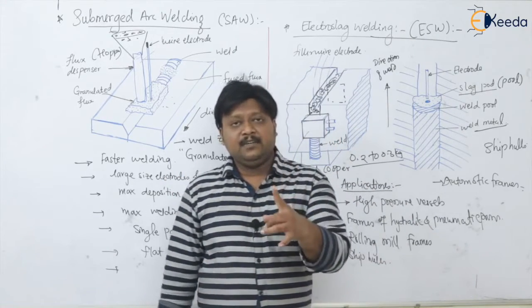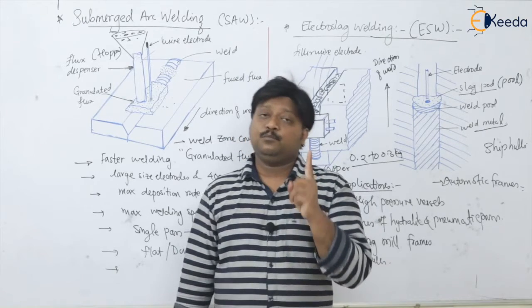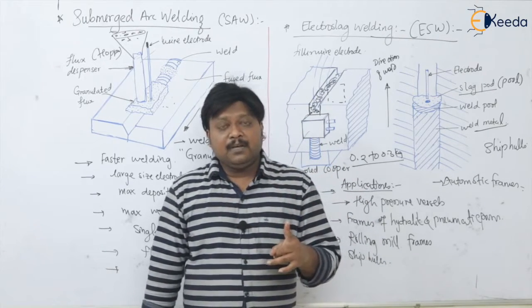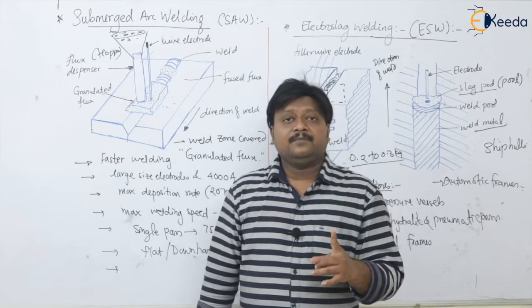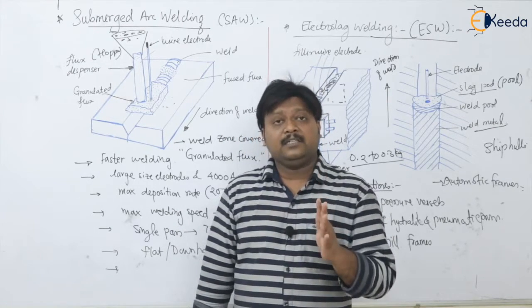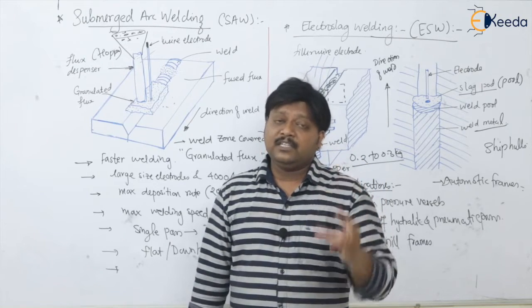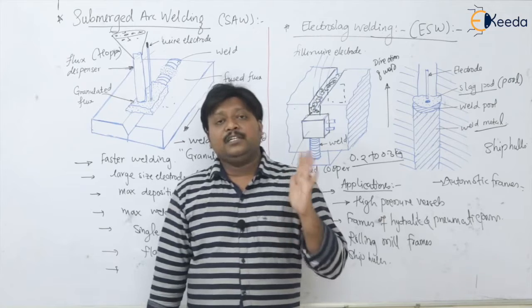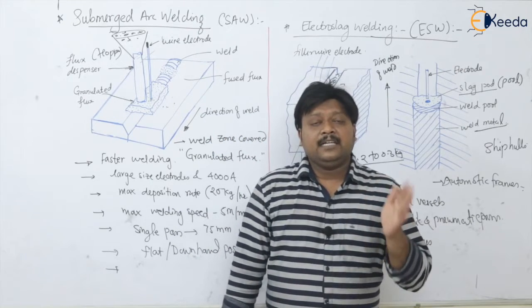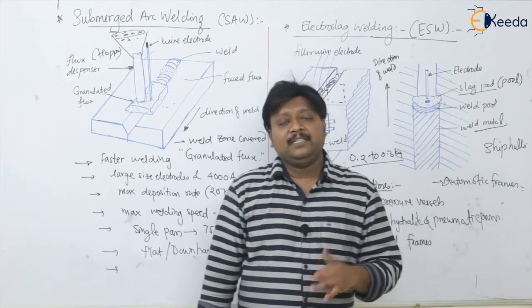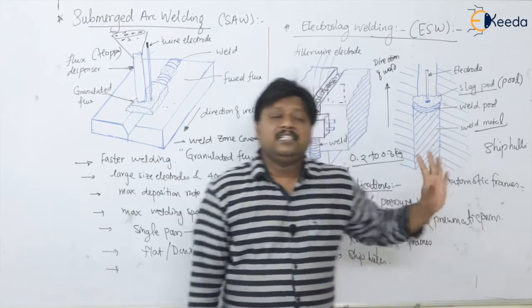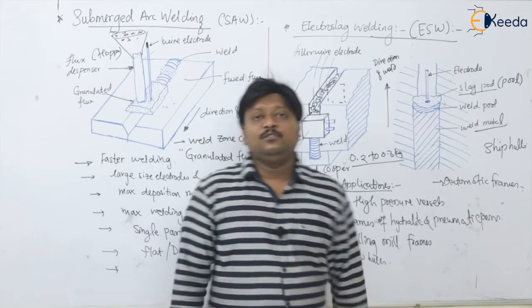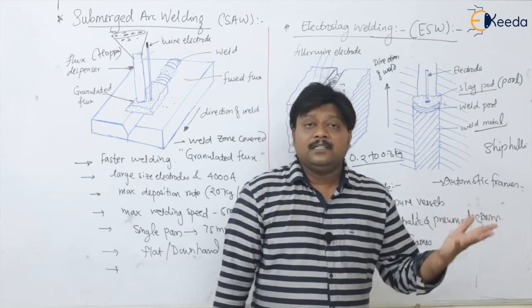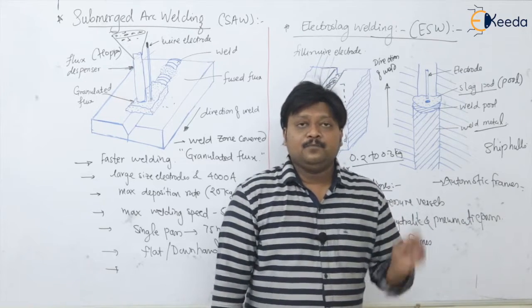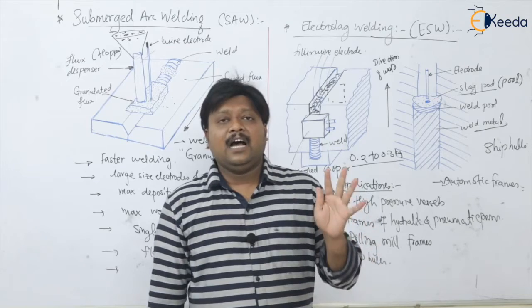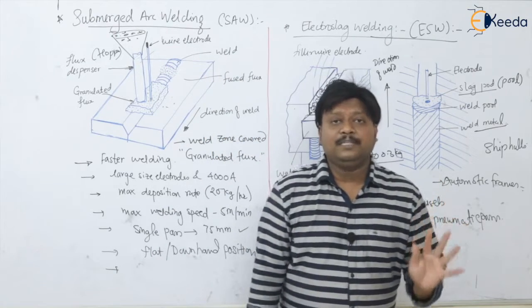So TIG welding in a single pass without filler rod, we can weld a plate thickness up to 5 mm. MIG welding in a single pass up to 30 mm. Or more than that we can go, but weld spatter will be high because we have to reduce the welding speed again, but up to 30 mm it is okay for the MIG. Then SAW up to 75 mm in a single pass very nicely, and ESW in a single pass up to 200 mm very nicely. Okay, so these are the arc welding processes we have completed. Thank you.